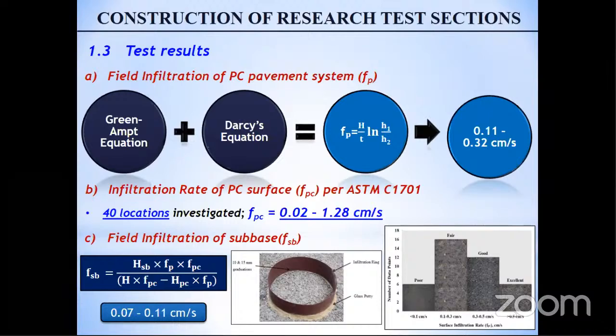Once these two tests were done, we tried to compute the infiltration rate of the subbase. Now, what we had was the infiltration rate through the system and the infiltration rate through the surface. The other task that remained was the computation of infiltration rate through the subbase layer. So in order to accomplish that, we utilized the layered permeability concept available in soil mechanics, and an equation was derived, as can be seen on the screen. And it was observed that the permeability rate of the subbase was somewhere between 0.07 and 0.11 centimeters per second, which is slightly lower as compared to the surface infiltration rate. But this may be attributed to the presence of fines, which were used to create a uniform platform for the construction of the pervious concrete layer.